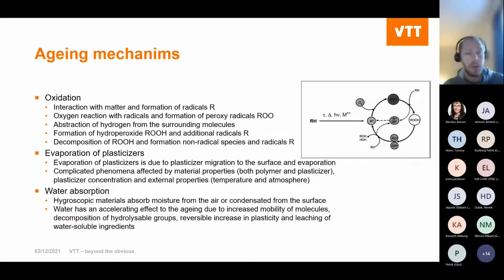Then third, we have water absorption. Hygroscopic materials can absorb moisture from the air, or moisture which is condensed on the surfaces. And water also has several accelerating effects on the aging. Mostly it increases the mobility of the different molecules in the polymer. It can decompose the hydrolysable groups. Then you can see a reversible increase in plasticity due to the ingress of water, and the water can also cause leaching of water-soluble ingredients. So that can be either a good or bad thing from an aging perspective.